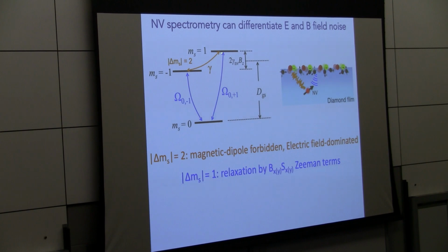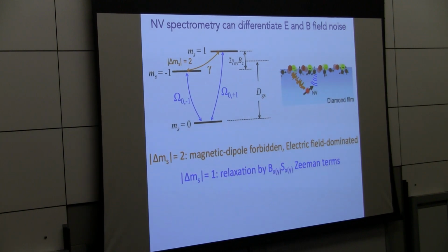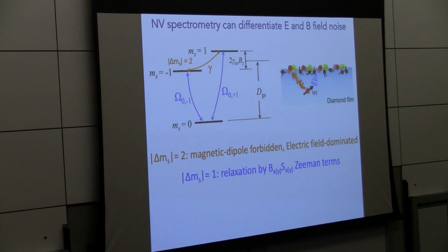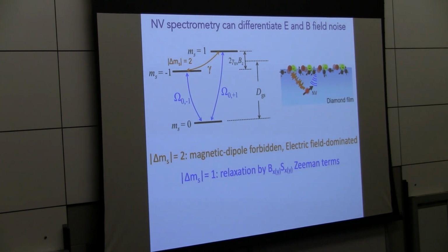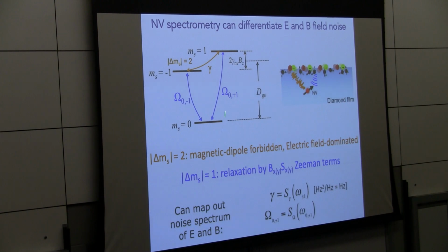As I've already mentioned to you, relaxation can be induced between these two states by fluctuating magnetic fields at that frequency. But one can also get relaxation between these two states, and in this case, relaxation is dominated by electric field terms. Again, I have a delta m equals 2. The angular momentum changes by 2, so that's first order magnetic dipole forbidden. So one can use the relaxation rates of this two-level system and this two-level system to probe the nature of the decoherence spin bath, as well as the frequency spectrum. Right, so that's basically shown here, and we can also vary these splittings with a magnetic field to map out that frequency spectrum.